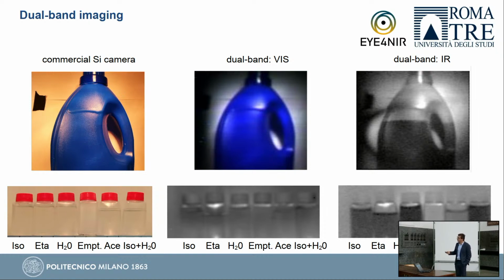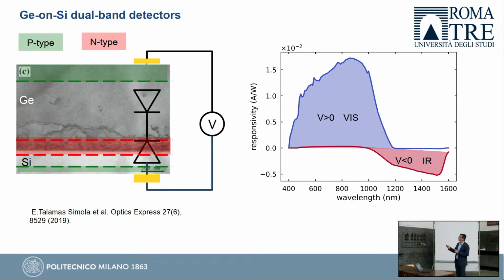Another experiment is here. So here you have a series of other small bottles filled with different substances: isopropanol, ethanol, water. This is empty, acetone, and this is a mixture of isopropanol and water. They all look transparent in the visible light. This is actually one of the reasons we cannot bring water bottles on airplanes, because there is no way of telling quickly if it's water or acetone, for example. And if we use our detector in the visible, we have the same kind of information, so they all look the same, more or less. But again, if we switch on the infrared light, we see that now these bottles have different colors, and actually you can train a classifier to distinguish what is what in these bottles. And this is using essentially just the positive or negative bias.